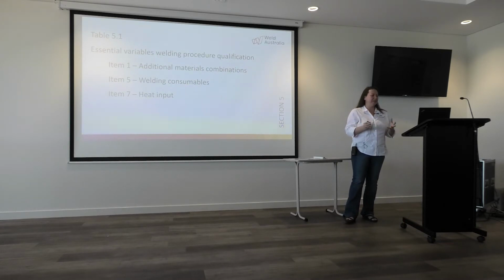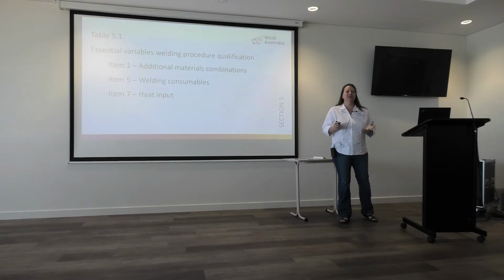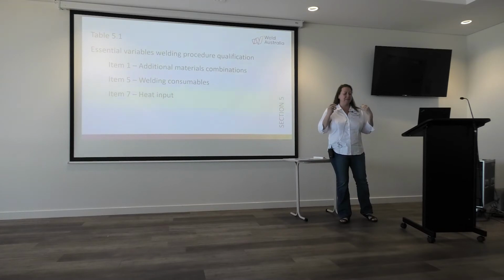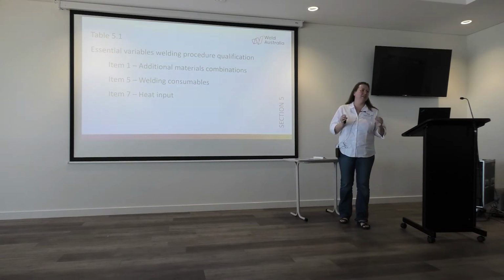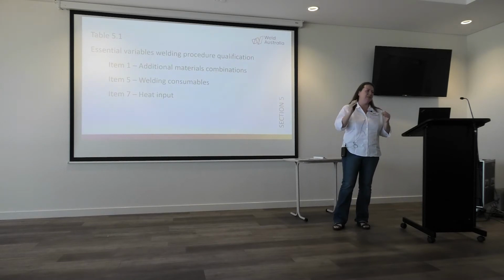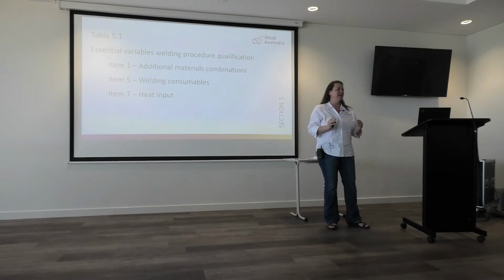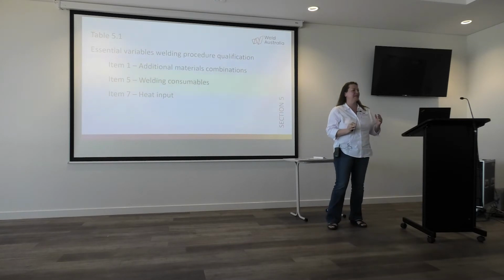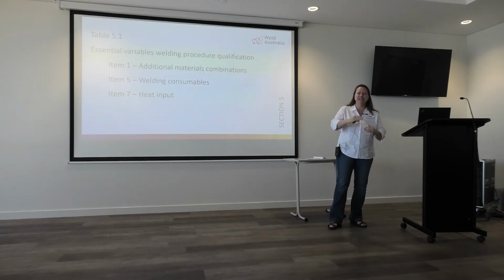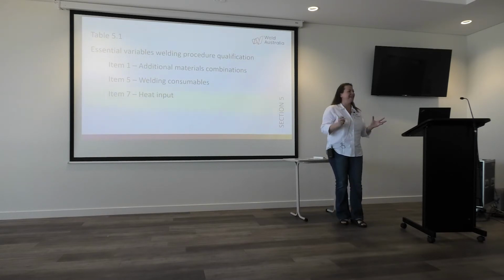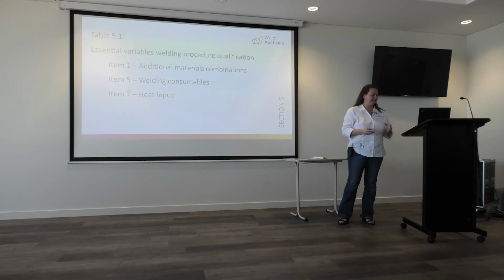And then under heat input, essential variables are now for each weld run. Because I actually dealt with a case where the manufacturer had specific requirements to meet minimum toughness requirements and maximum hardness, and he was very upset when his client's inspector showed up without saying hello, but went straight to where the welder was welding at 4 kilojoules per millimeter instead of 2. And he said, no, but the average heat input over the whole butt weld meets the requirements. So additional wording was added to make sure that it's per weld run.